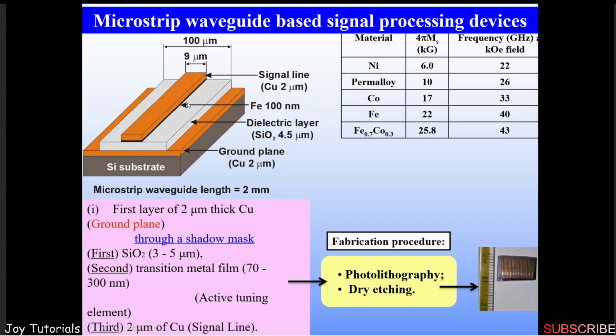And if you regulate this magnetic layer, one can have an operating frequency in different microwave ranges. What you can see here is the operating frequency using different kinds of materials. It is not just limited to ferromagnetic materials like nickel, permalloy, cobalt, iron, or the alloys of iron and cobalt, but you can see here the range of frequencies we can go up to. We can even go up to 43 gigahertz, which is well in the millimeter wave range.